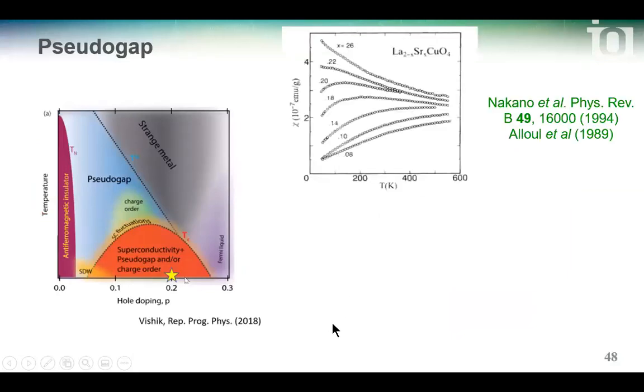So the pseudogap: if you look at the spin susceptibility as a function of temperature, and you look in your textbook, you will see that it's supposed to be Pauli susceptibility, so it's independent of temperature. Here, there's clearly a loss of something, some spectral weight at the Fermi level. In the standard textbook, it's just the density of states. So if you interpret it like that, there's a loss of density of states.